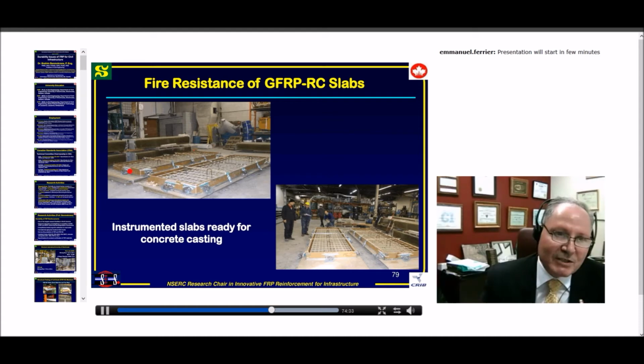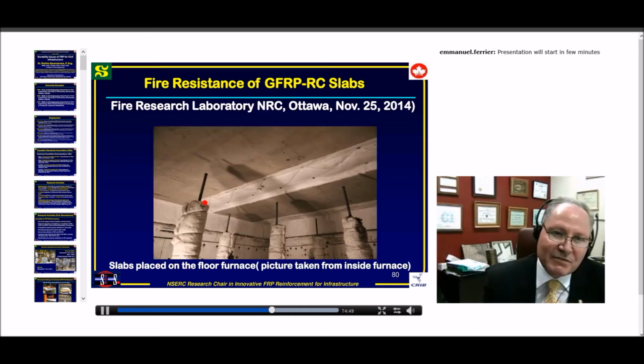We made the slabs with two products, one sand-coated GFRP bar from Pultrall and one deformed bar from BP Composite in Alberta. It's the same reinforcement in both, 16 millimeter bars spaced at 150. The span of the slab is 3.8 meters. As you can see here, this is the Fire Research Lab in Ottawa. It's a recognized lab used by all the Canadian industry and also by the government. This is the only lab available for fire research testing in Canada. You can see here the two slabs placed on the floor of the furnace, with the picture, of course, taken from the inside.